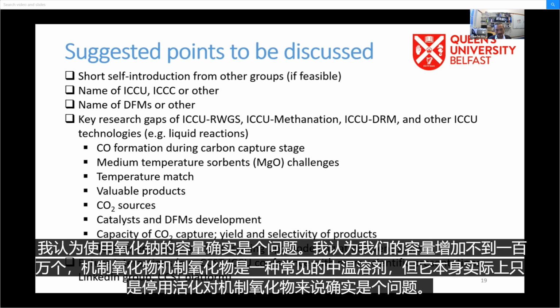Okay, I think the next issue I want to discuss is the capacity of the sorbent. The most used sorbent is calcium oxide based at high temperature. We understand its capacity is quite high, higher than 10 millimole per gram of CO2 capture. But when we come to low temperature CO2 capture, like for methanation or medium temperature methanation, I think the capacity really is the issue. Using sodium oxide, we get less than 1 millimole per gram of capacity.